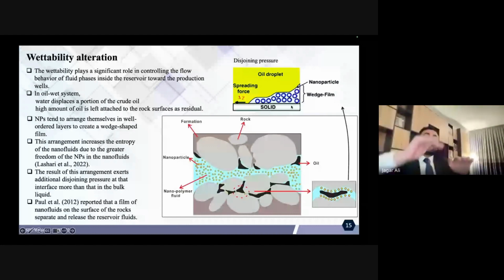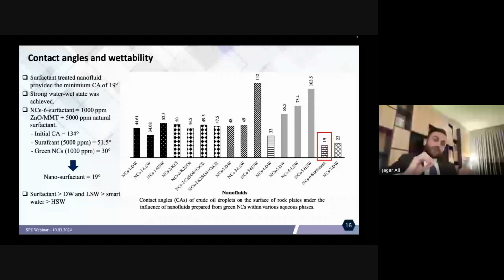And then we try to reduce it by injecting nanofluids to be less than 90 degrees. So this is how it happens. When nanoparticles are injected inside the porous media, they will arrange themselves at the interface between the oil droplet and the solid surface. They create a wedge film which can create higher disjoining forces, and it will make hydrocarbon free and moved towards the production well to be produced. This is how it works inside the porous media.